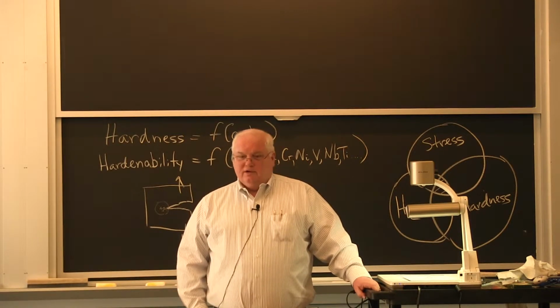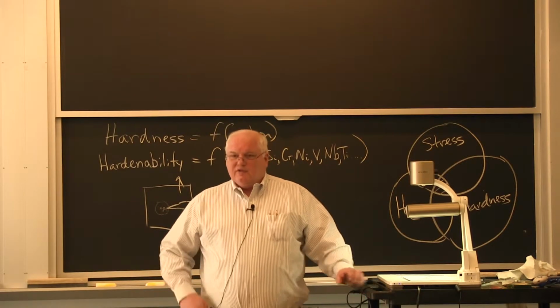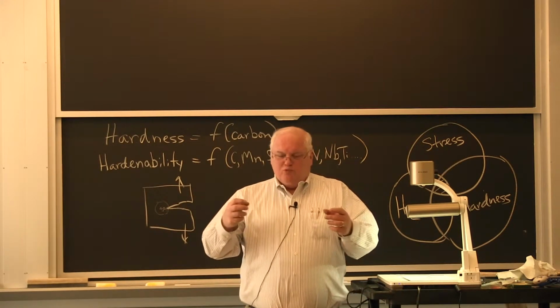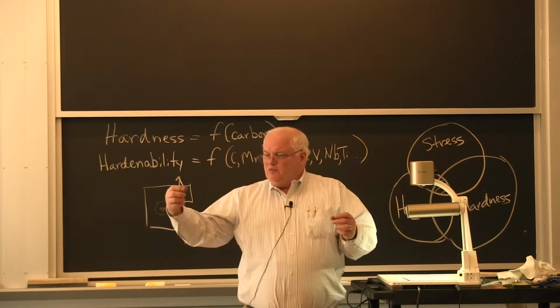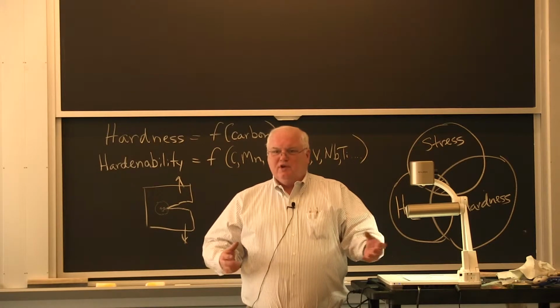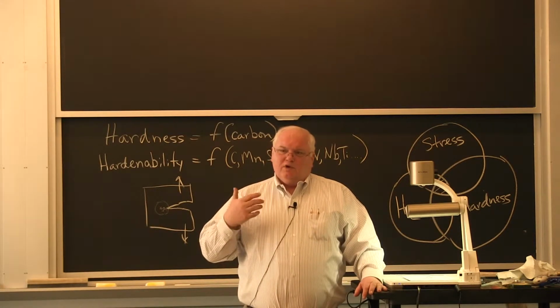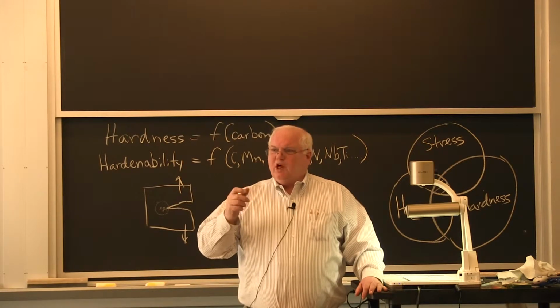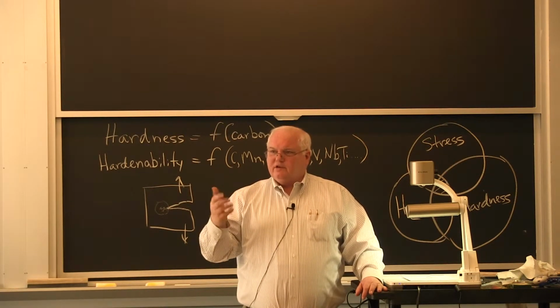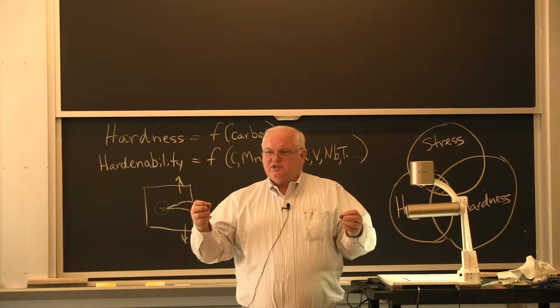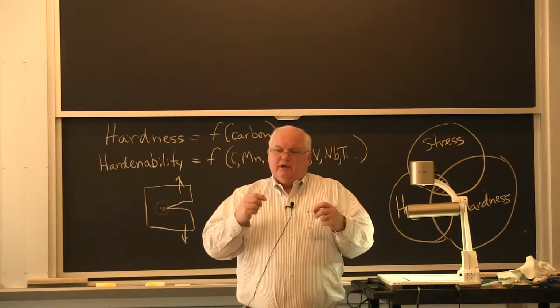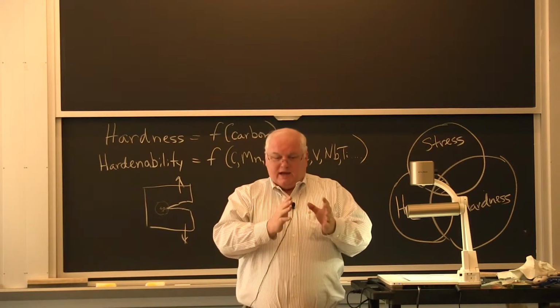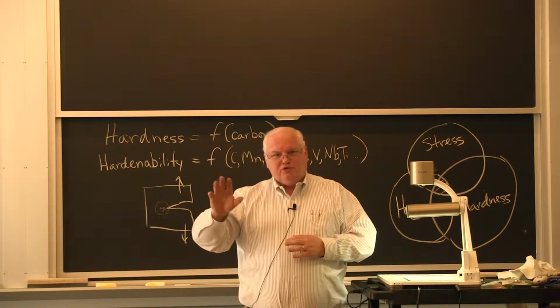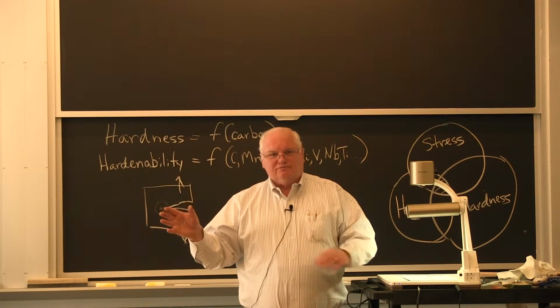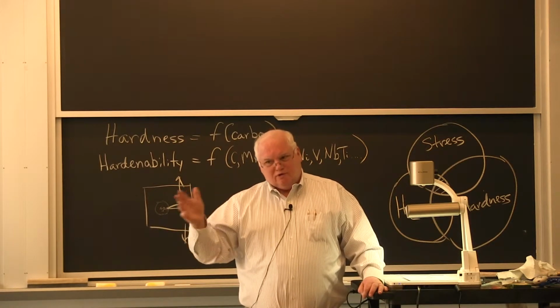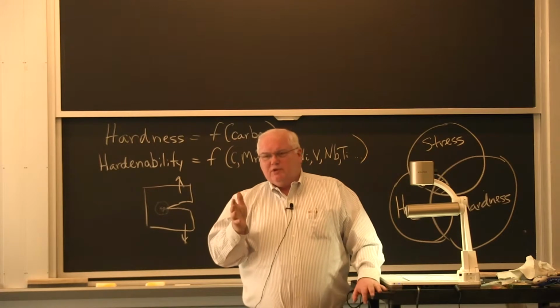I will tell you about another company that makes engines, and they have something called a pea shooter, which is nothing more than a drive coupling, a spline shaft that runs from the engine to the transmission of the helicopter. They were doing a nitrided heat treatment on these splines. You were asking about localized hardening. One way to harden the surface of a steel on these little spline gears is to nitride them. They had a spec, and 4 or 5 of these pea shooters cracked in brittle fractures, and a couple of them caused the helicopter to crash. Wasn't a good day for the people in the helicopter.